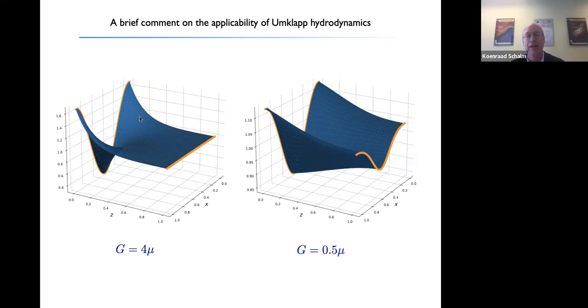Here's an example of the profile in the radial direction of such a black hole, where I have taken a lattice vector which is 4 times the average chemical potential. And you see immediately it renormalizes very rapidly away, and essentially at low temperatures, or close to the horizon, this is just a completely homogeneous system. This is the naive expectation you have based on the UV insensitivity of effective quantum field theory in the infrared. What happens at these lower lattice vectors is that the system thermalizes, or classicalizes, or hydrodynamizes, at scales where you still have a very large lattice vector left. And then the quantum renormalization, the quantum screening, ends. And so it stays imprinted for a very, very long time down to the lowest temperatures. Actually, you can prove in the system that nevertheless, at the lowest possible temperatures, this will still become a homogeneous system. It's just that the onset is delayed for a very, very long time.